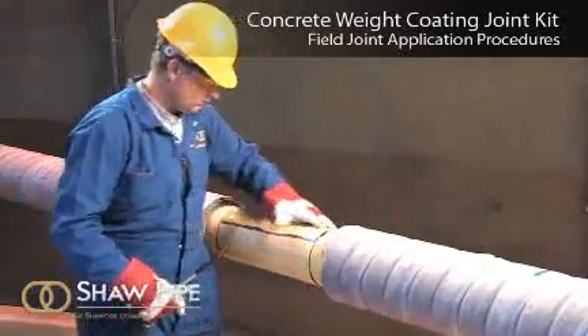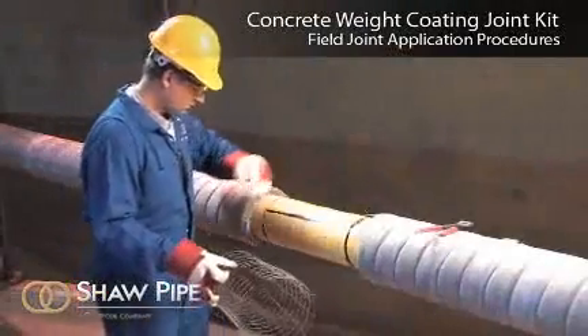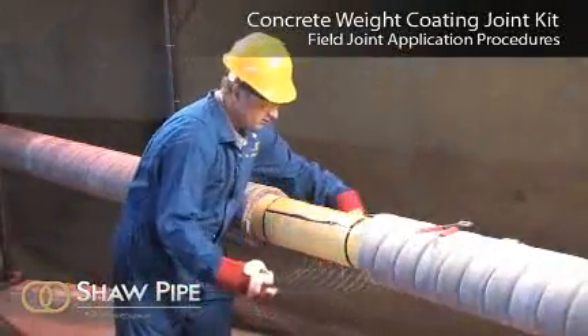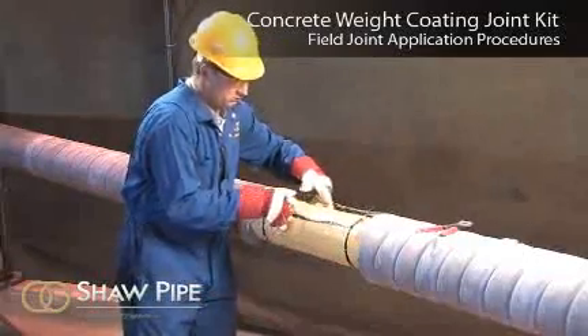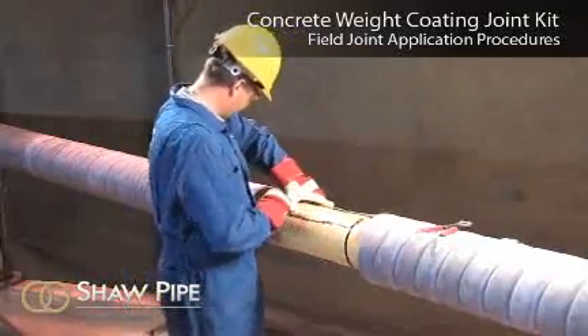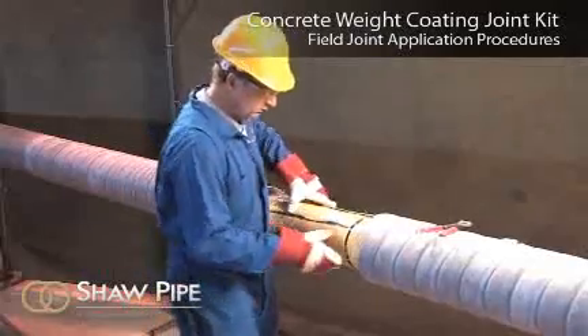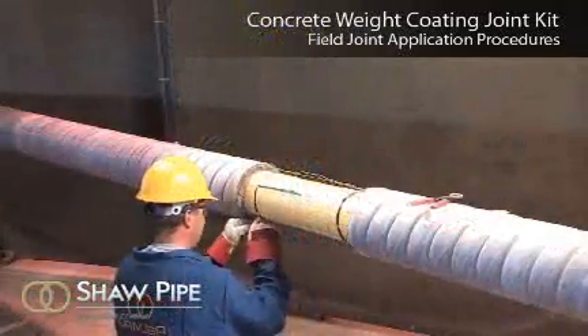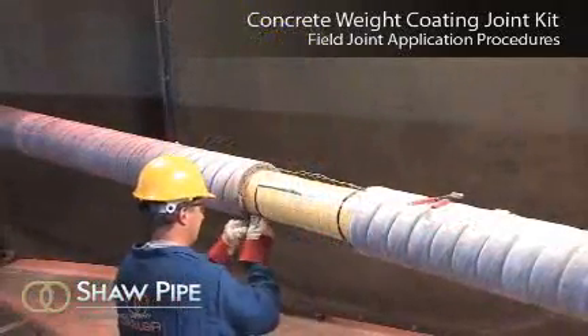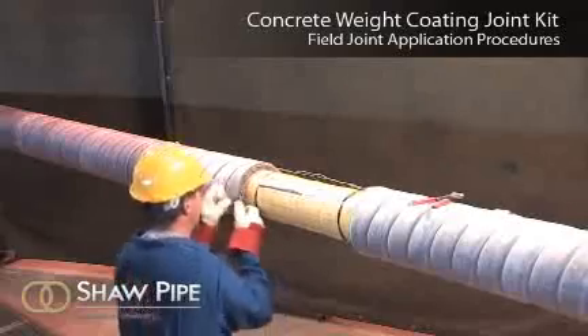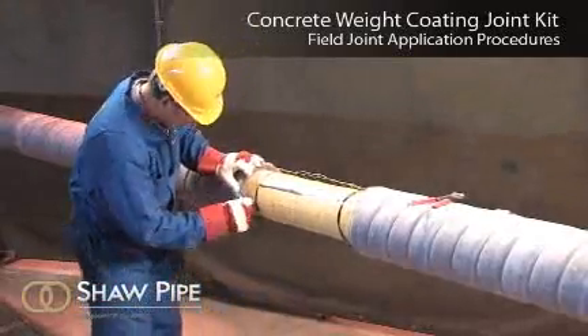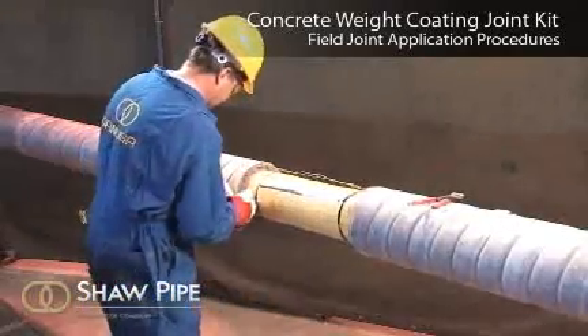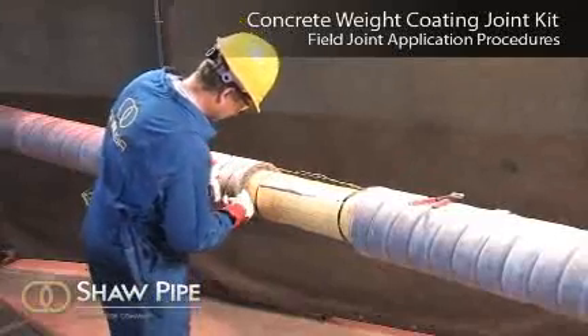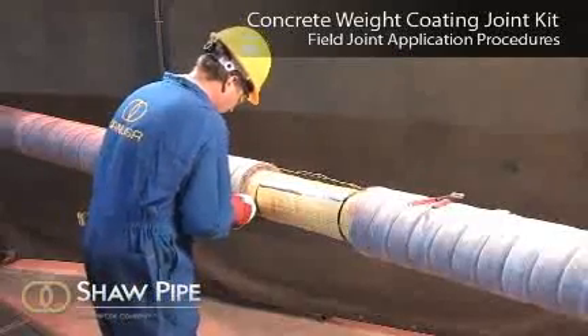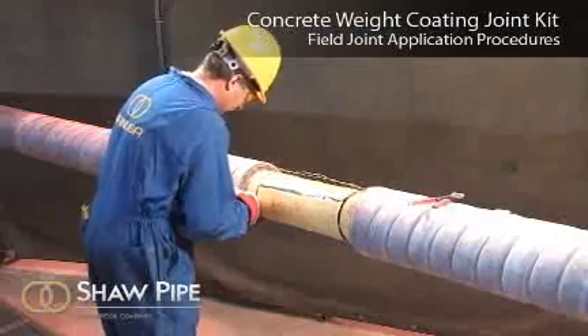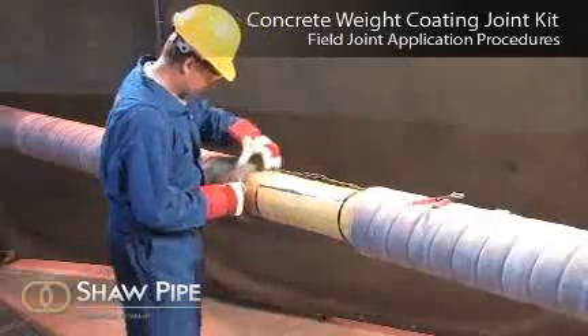Any and/or all quality inspection tests that are required must be completed before the installation of the concrete weight coating joint kit. Install the concrete weight joint kit by wrapping the pre-rolled reinforcing wire cage around the joint area and attach at both sides to the exposed mesh at the pipe ends. Ensure that the cage is held securely and is uniformly spaced from the pipe surface at approximately 1/2 of the concrete thickness.